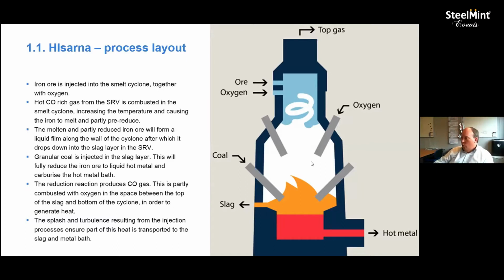In the cyclone, hot carbon monoxide rich gas from the bottom part of the process rises and is post-combusted by this oxygen, and the temperature increase that results in instantaneous melting of the iron ore. And it also means that the iron ore gets at least 10% pre-reduction, and depending on the gas composition, in particular the carbon monoxide content, it can be up to about 25% pre-reduction. And the liquid iron then drips into the slag layer here.